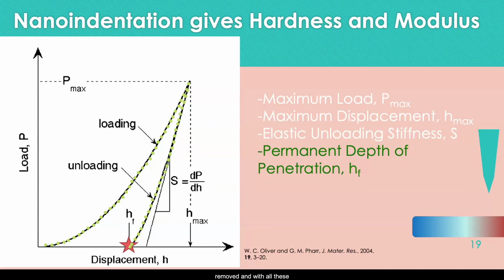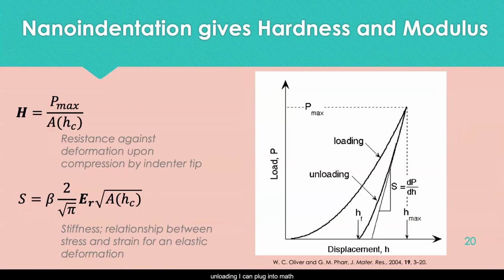And with all these quantities and understanding the expected shape of an elastic curve from the unloading, I can plug in some math and get the hardness, this H value, which is the resistance against deformation upon compression by the indenter tip, and this E sub R value, which is the modulus. It's a measure of stiffness, the relationship between stress and strain for an elastic deformation. And I can use all of those values that I've collected to determine those values and see that both hardness and modulus are enhanced by the PVD process under particular temperatures.